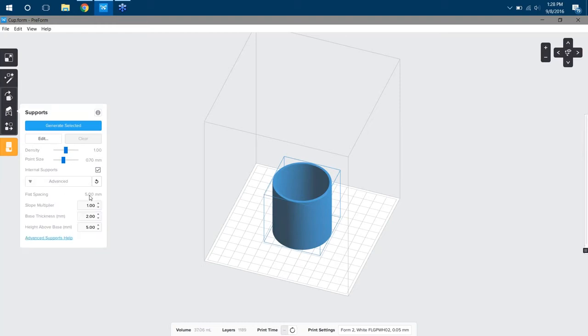Below this, we have point spacing under the Advanced tab. This is basically a measurement of how many points per X millimeters. So you notice as I increase the density, I get 1 point every 2.5 millimeters, whereas if I decrease the density, I'm getting 1 point every 7.5 millimeters. So it's just a little bit of extra info that you can use. Below that, we have the slope multiplier, which changes how many supports are on a slope face. Most of these you don't really have to change. That one especially, I've never had to change it.